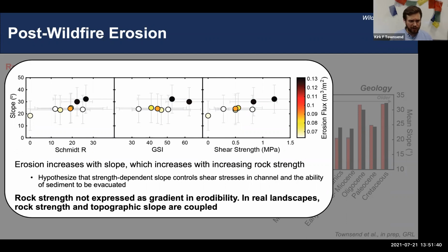And again, here we're finding that rock strength is not expressed as a gradient in erodibility, right? That was kind of the typical landscape evolution assumption. In real landscapes, we see that rock strength and topographic slope are coupled, and then that sets the stage for the erosional response later.